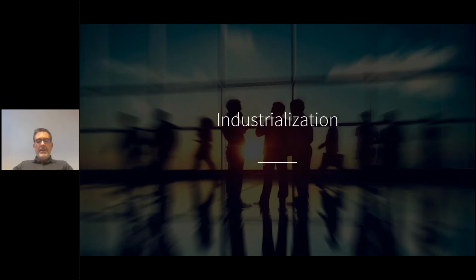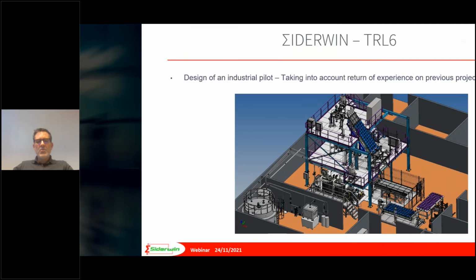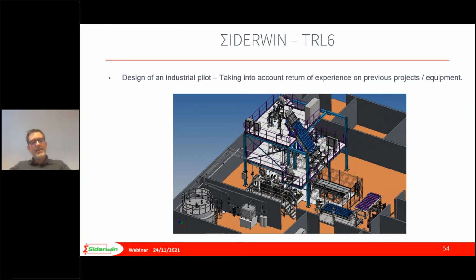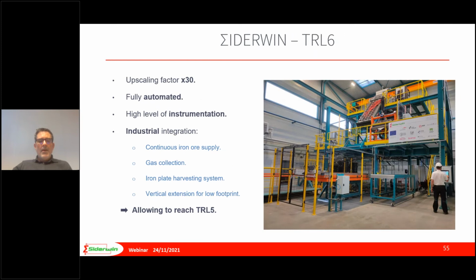So now we were ready to move to the industrialization. So this was performed by people from John Cockerill. As you can see here, they were able, using CFD simulation for the pilot, but with their experience, to design an industrial pilot, as you can see here on the picture. So this pilot was designed with experience from previous projects, and from all the simulations we did during this project. And then we were able, as you can see here, to build the pilot itself with an upscaling factor from ULCOWIN to SIDERWIN of 30, with a high level of instrumentation.